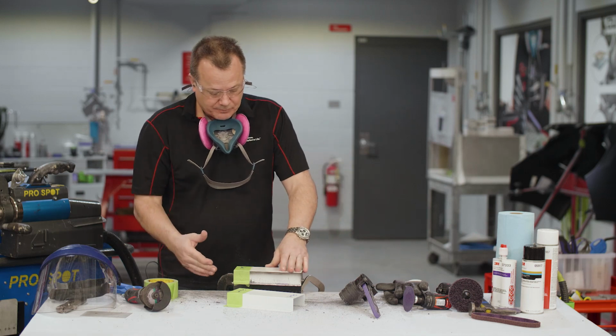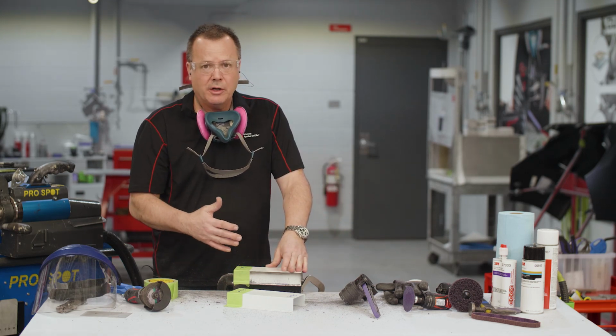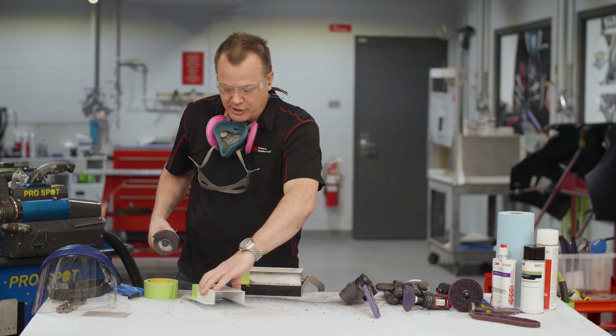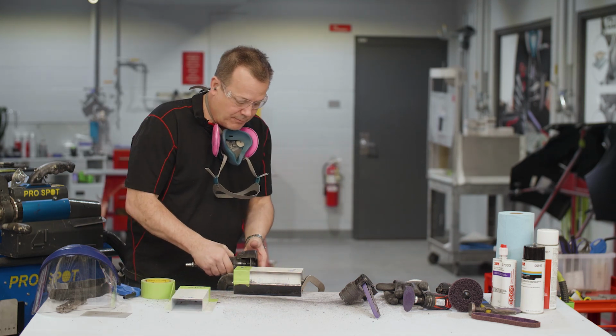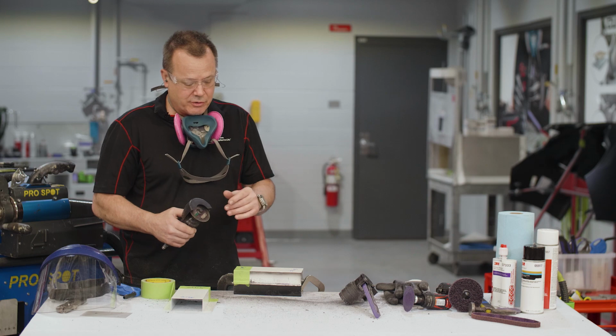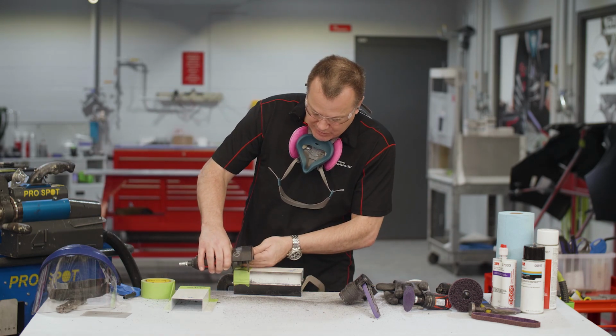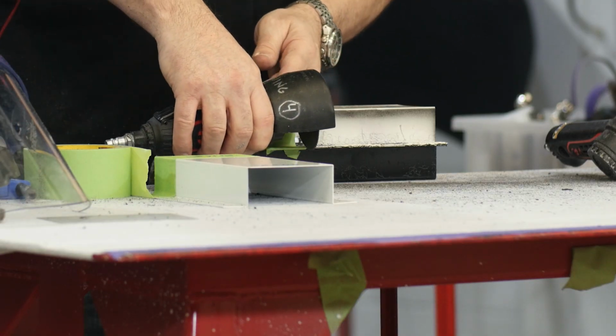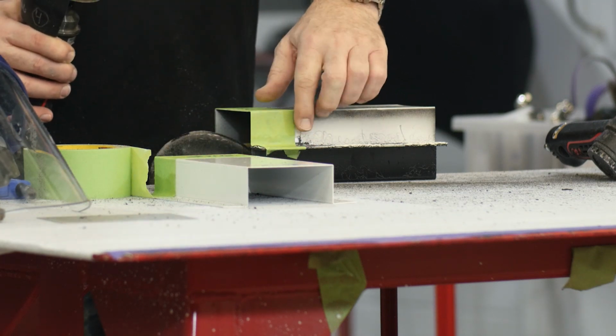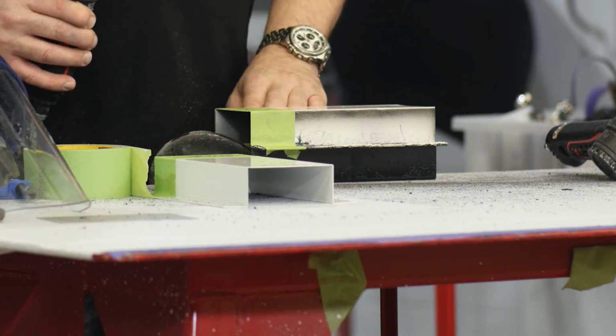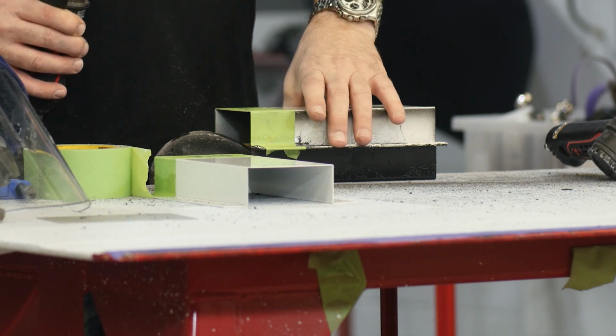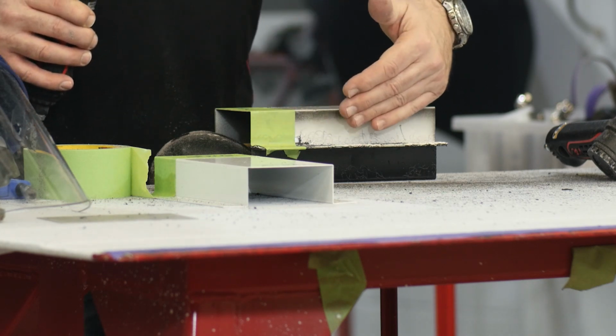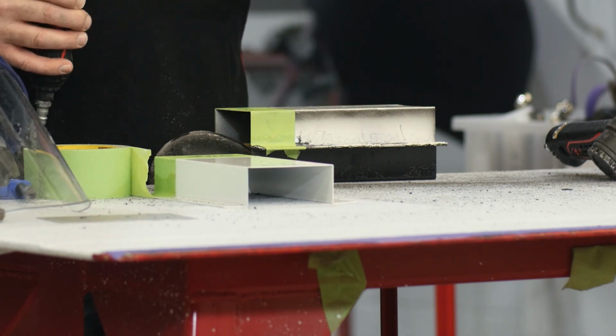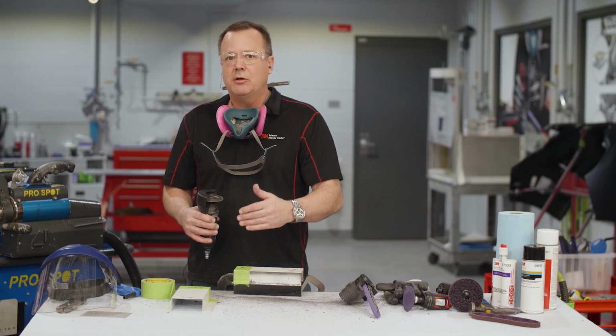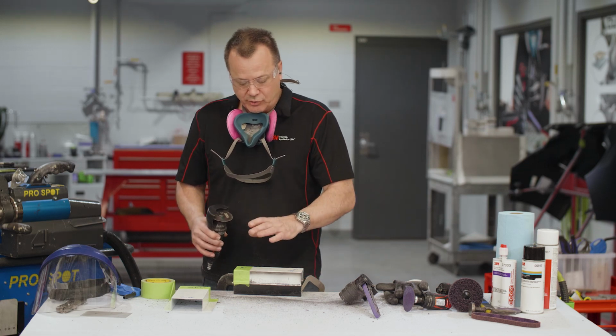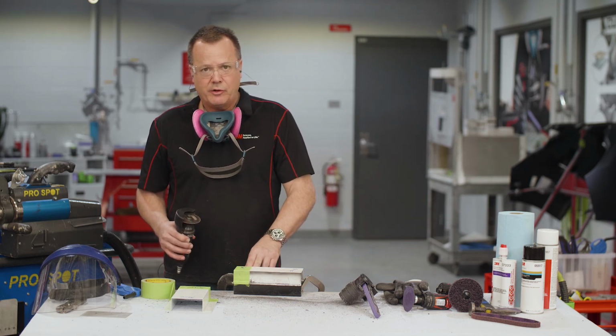The next step here, I'm going to take my cutoff wheel and I'm going to cut as far through this as I can using my cutoff wheel. Now the difficulty we're going to run into here is that I can only cut so far with my cutoff wheel before I start cutting into this bottom flange. And the key to this repair is not to damage the bottom flange on the host panel. Again, if we cut through that part, it may have to be replaced. Sometimes they're ultra high strength steel. Once you cut it, it's done. You can't weld it. So we have to be very careful about cutting through that bottom piece.